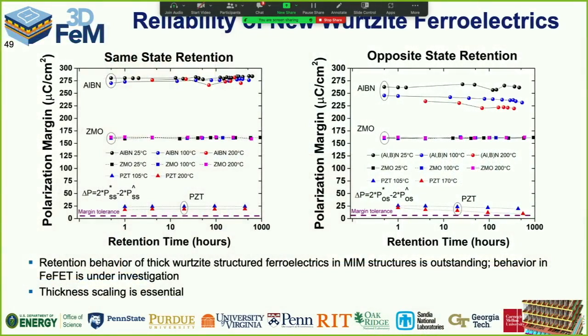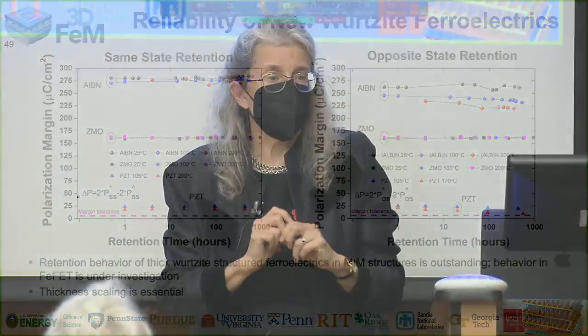So will this thing actually hold a polarization? It's very useful when you set a memory state, if that memory state can be retained, so I could come back and read it later on. Otherwise, my memory develops amnesia and I'm unhappy. So this is the standard retention characterization for ferroelectric random access memory. You measure in the same state. So you put the polarization in the up direction, you bake it there for a while. And when you do that, all the point defects and everything that's going to move tends to move to stabilize that state. And so when I come back and try and read that state, it tends to be really stable.